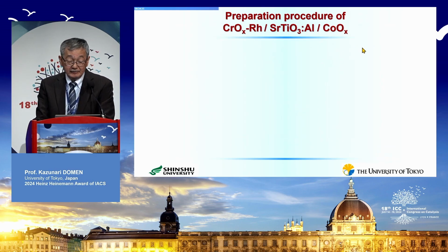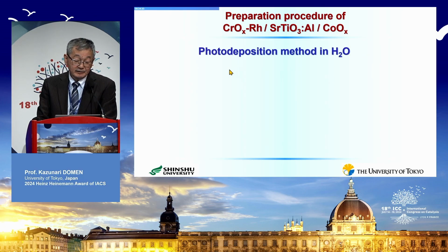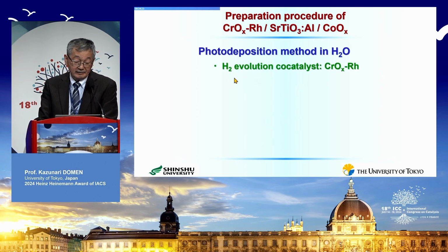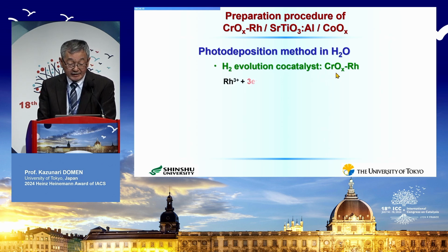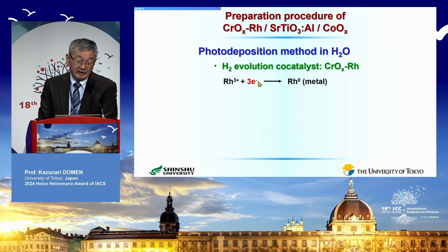Now, let me introduce how to prepare this type of photocatalyst in more detail. As I said, we use a photodeposition method for all the metallic components of the co-catalyst in aqueous solution. At first, we construct the hydrogen evolution co-catalyst, that is rhodium and chromium core-shell structure. The first reaction is metallic rhodium nanoparticle deposition using photoexcited electrons to reduce rhodium-3+. However, if these metallic rhodium nanoparticles are exposed to the surface, the reverse reaction from the product of hydrogen and oxygen to form water molecules proceeds.